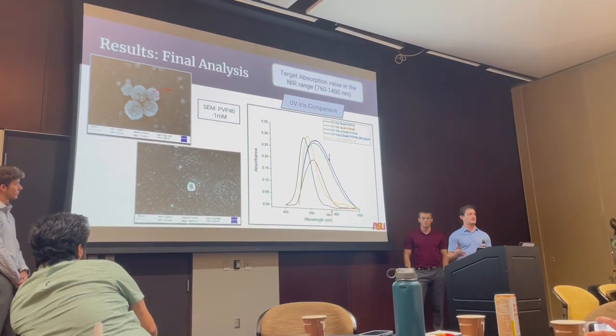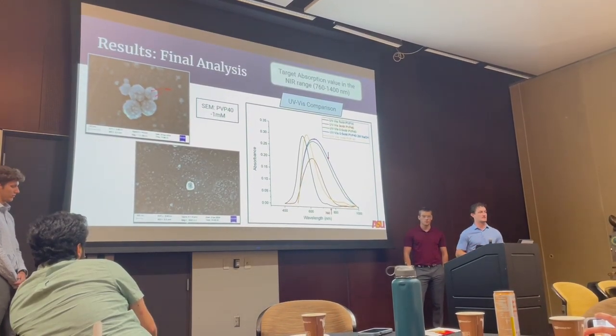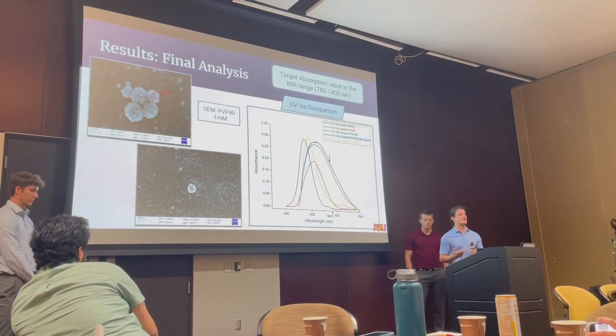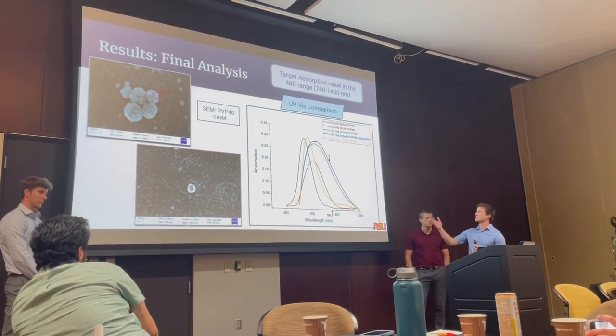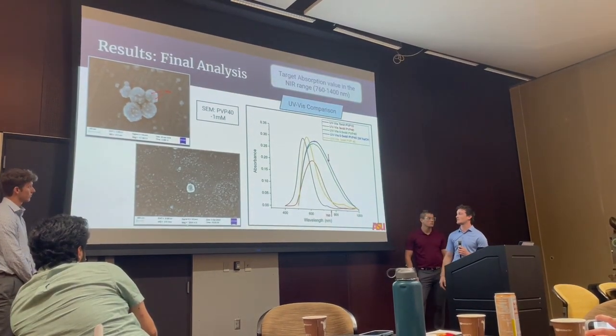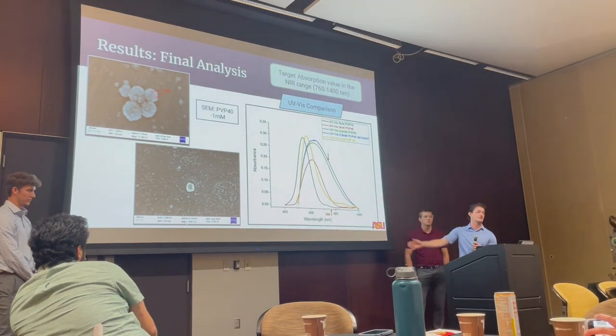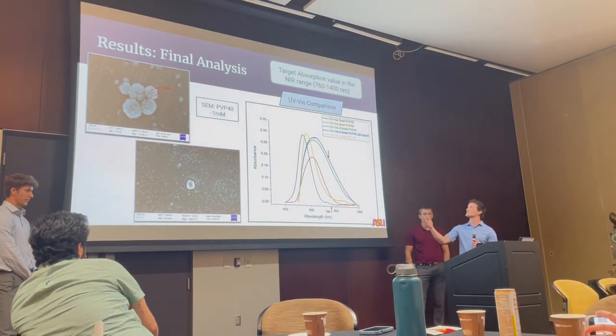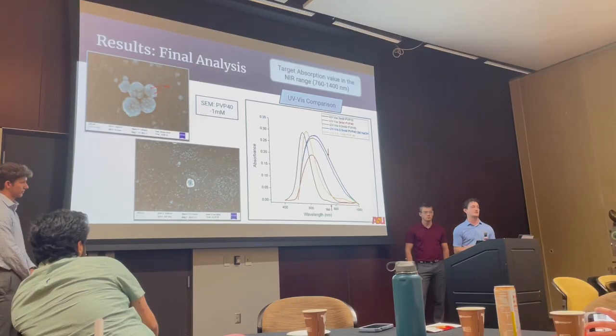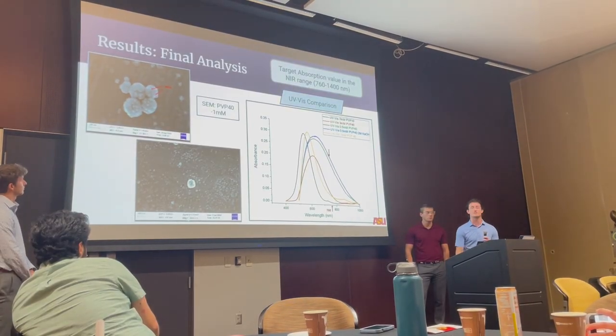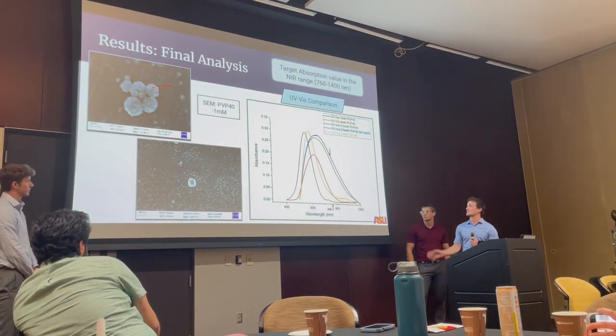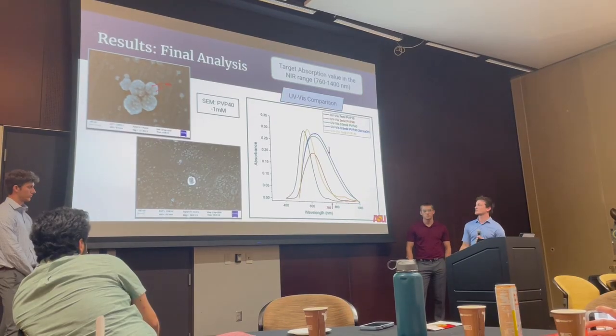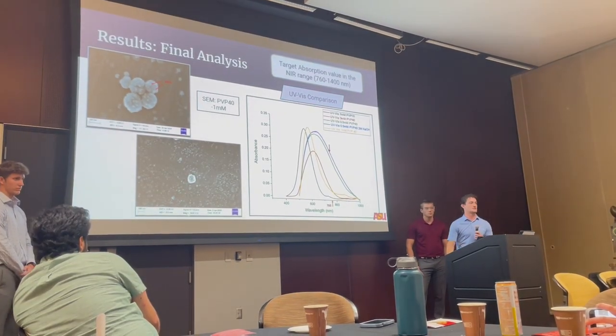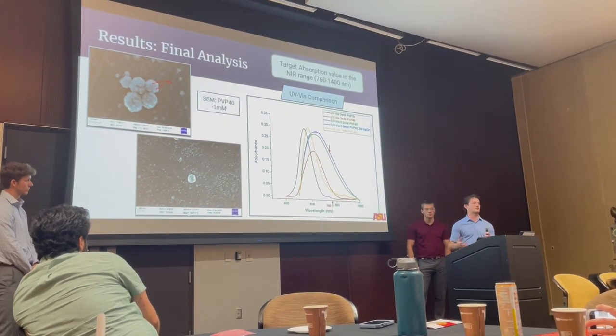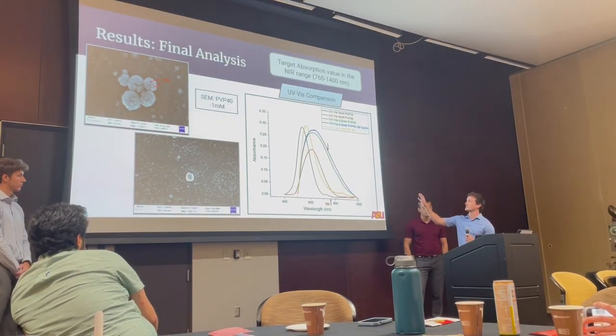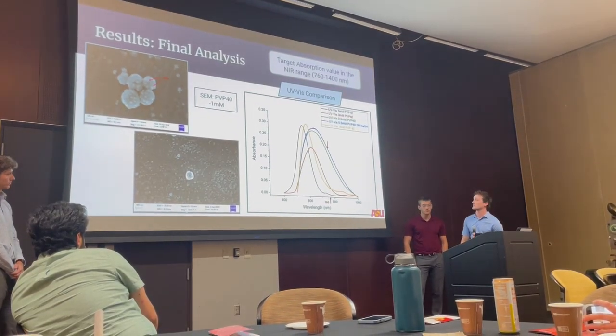and the concentration we wanted to stick with, we decided we needed to test their absorbance using the UV-vis to see what was actually going to absorb that near infrared light. You can see the red line is our 3 millimole PVP-40, which is still below our target range of 760. So we continued to decrease the PVP-40 concentration to 0.5 and 1 millimole. As we did this, we had a major right shift to where we were actually now absorbing light in that 760 range. So our particles were able to absorb that near infrared light, and the blue and green lines there are our 0.5 millimole concentration.